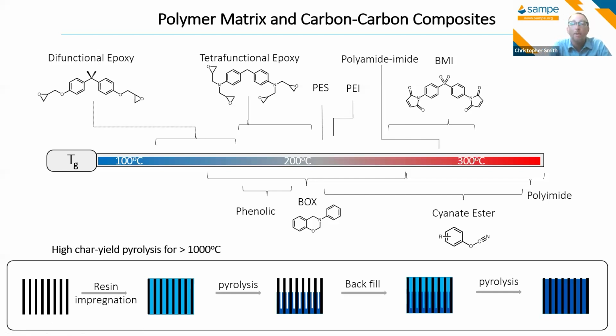So you can also make carbon-carbon composites out of these. The image on the bottom, it's showing a pyrolysis method for making carbon-carbon composite. So you start with your reinforcement, whether that's carbon fiber or glass fiber or other, and then you infiltrate it with your resin or your thermoset matrix, and then burn off the organics at high temperature. So you're left with some voids, but you're left with a lot of charred carbon that stays within the part. So you can backfill that with more resin and continue this process of backfilling it and burning it off until you have a 100% mass of carbon that will maintain its weight and stability in greater than 1,000 degrees C.